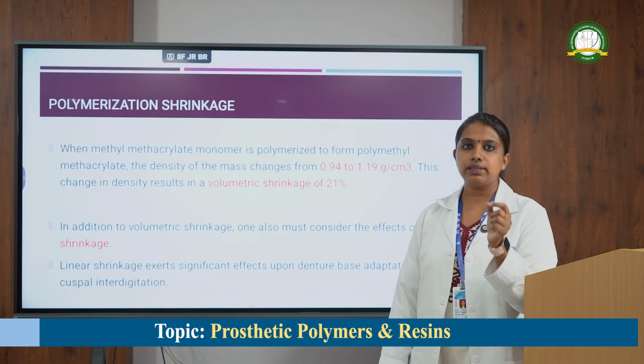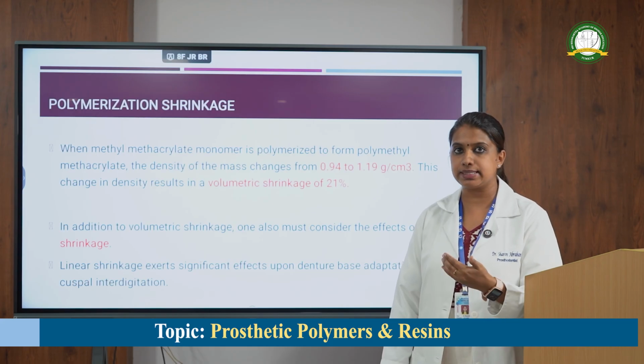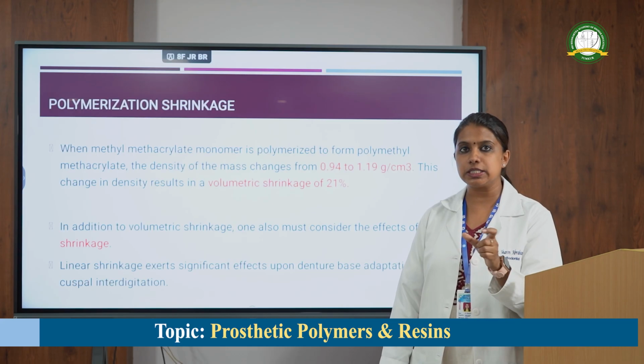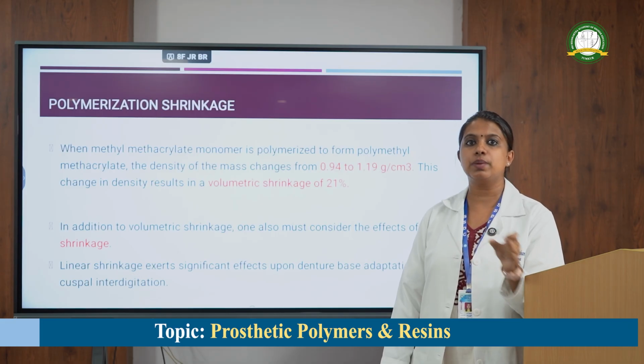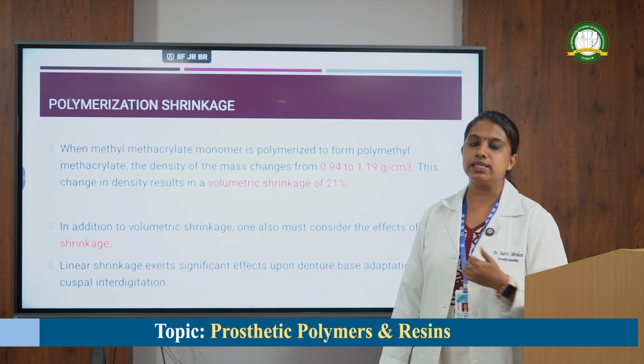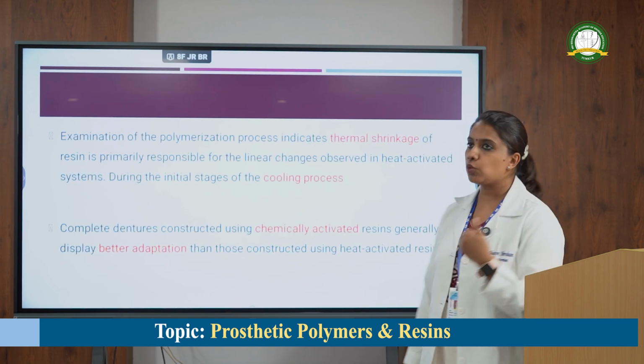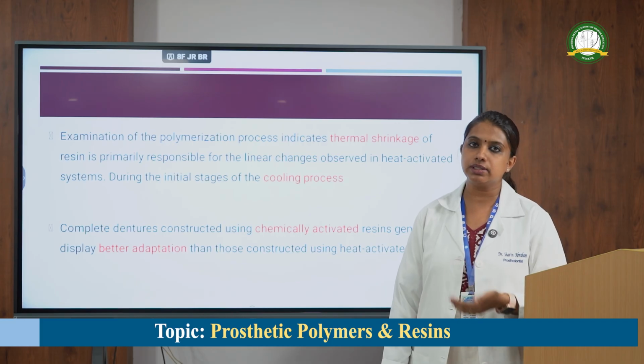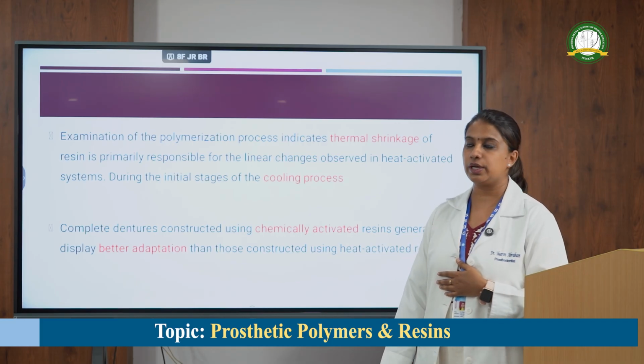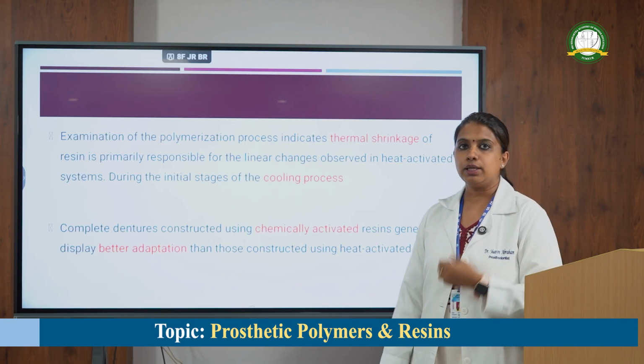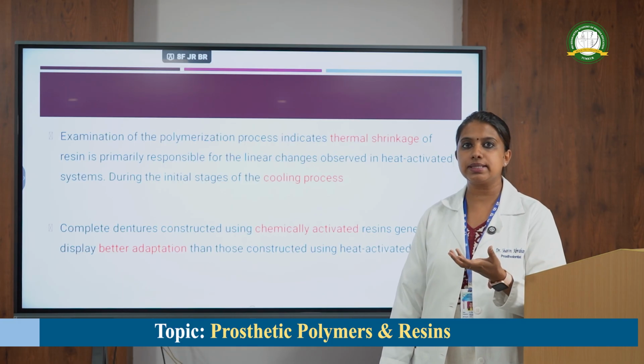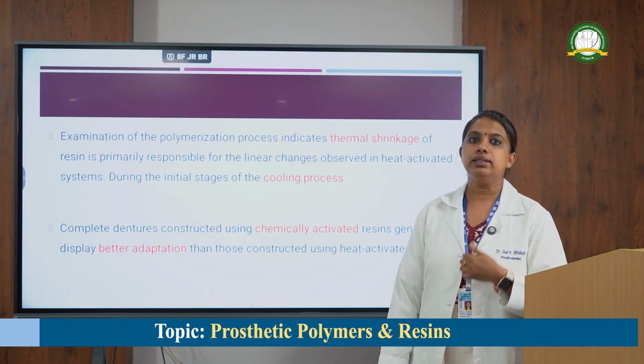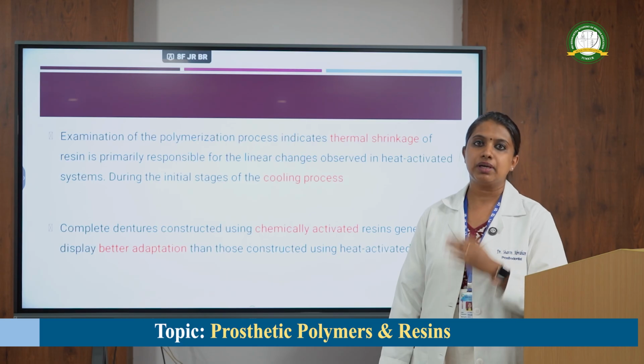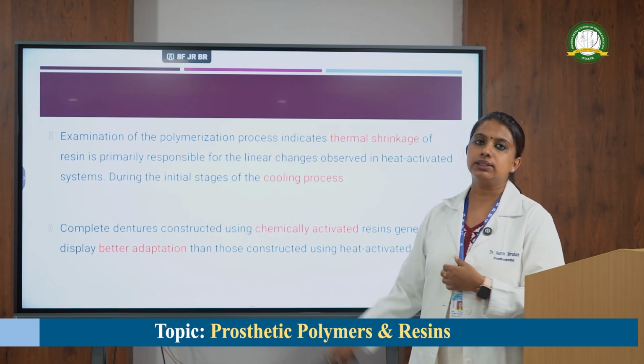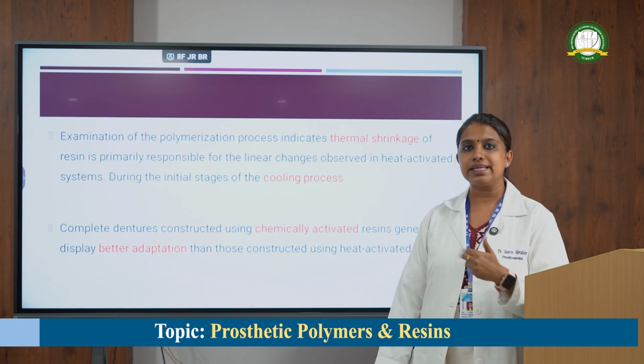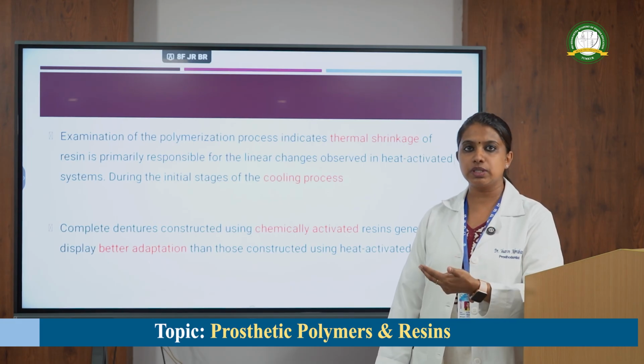Now, how did they identify that? They marked some reference points before polymerizing the resin, and they checked the distance between these reference points after polymerizing. If there was a reduction in the distance between these reference points, it was concluded that there was a linear shrinkage. Now, along with linear and volumetric shrinkage, thermal shrinkage was also evident, most commonly with the heat cure resin when it was polymerized using a water bath or a microwave. Thermal shrinkage most commonly occurs after polymerization. You have to bench cure the flask for at least 30 to 45 minutes and then run it under tap water. If you deflask it immediately after polymerizing, it leads to thermal shrinkage. And most commonly, thermal shrinkage is because of the disparity in contraction between the gypsum mold and the resins.